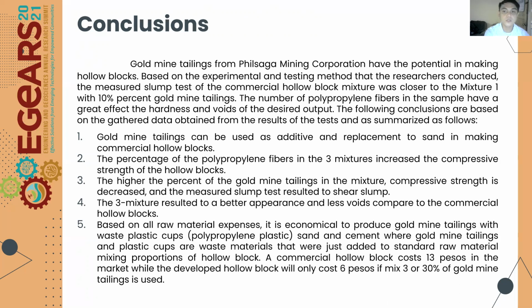The following conclusions are based on the gathered data obtained from the results of the test and are summarized as follows. First, gold mine tailings can be used as additive and replacement to sand in making commercial hollow blocks. The percent of polypropylene fibers in mixture 3 increased the compressive strength of the hollow blocks. Next, the higher the percent of gold mine tailings in the mixture, the more the compressive strength decreased and the slump test result went to shear slump.